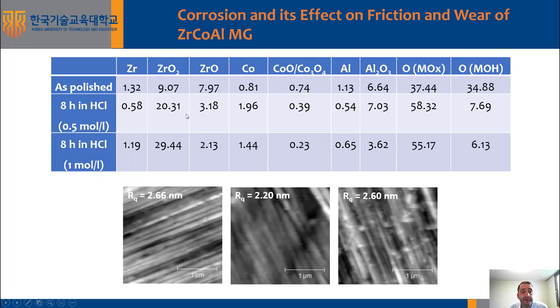So to finish this presentation, I would like to show you now some results obtained on zirconium, cobalt, aluminum metallic glass. The samples were produced by casting, so here we are dealing with a bulk metallic glass. Before scratching, these samples were mechanically polished, and we measured the topography in the as-polished state, and after immersion for 8 hours in hydrochloric acid solution with different molarities. In one case it was 0.5 mole per liter, and in the other it was 1 mole per liter.